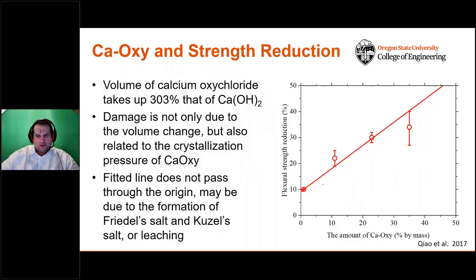Now, a couple of the things that you'll notice is we can measure the flexural strength of the paste. And if we expose these pastes to these de-icing chemicals, what you'll notice is a slight reduction even in systems without oxychloride forming. We tend to see about a 10% decrease, and this is simply because of the dissolution of the calcium hydroxide. So the calcium hydroxide just leaves the system, it dissolves, and we see a small decrease.